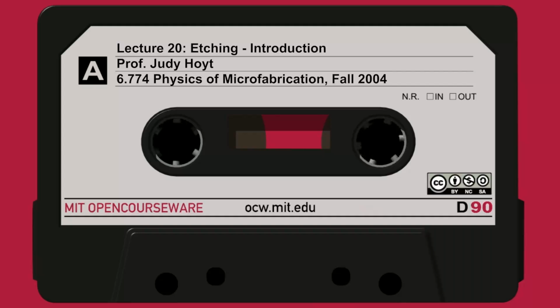And in fact, we can mathematically express the amount of anisotropy, how anisotropic the etch is, by defining this number here called A sub f. If you define this anisotropy factor, A sub f, to be 1 minus the lateral distance etched in a given time divided by the vertical, then in my diagram here, this would be 1 minus B over D. I etch laterally by a distance B and vertically by a distance D.